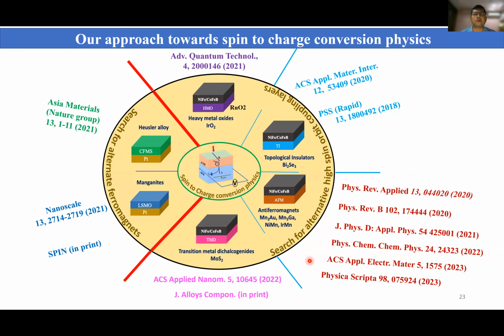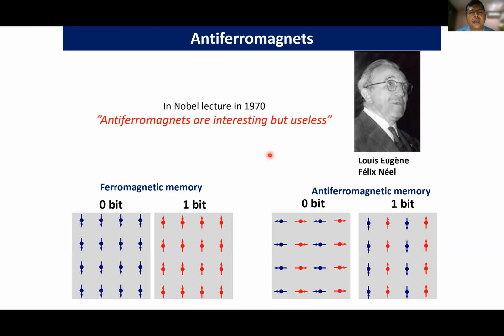Yes, this is a summary where we are exploring different types of high spin-orbit coupling materials, like iridium oxide, ruthenium oxide, topological insulators, different kinds of antiferromagnets, transition metal dichalcogenides, and so on. We are also looking for alternative ferromagnetic materials, because usually you consider cobalt iron boron or permalloy, which are low damping materials, but we are also looking at Heusler compounds, manganites, and so on. Now, going quickly to the field of antiferromagnets. As you know, this is the famous lecture of Louis Néel.